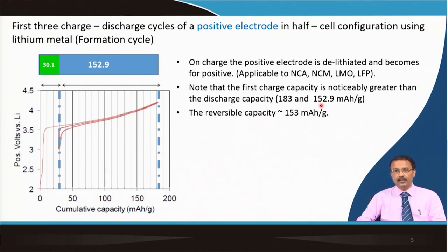electrochemical characteristics. So, we will term that this is the reversible capacity for the cathode material, and the part of the capacity that is not reversible is about 30.1 milliampere hour per gram in this case. That is happening because of several factors: lithium is coming out, the crystal structure changes, and then lithium is not finding the exact place where it was before. So, that reduces part of this capacity which you cannot get back. So, this is irreversible capacity.